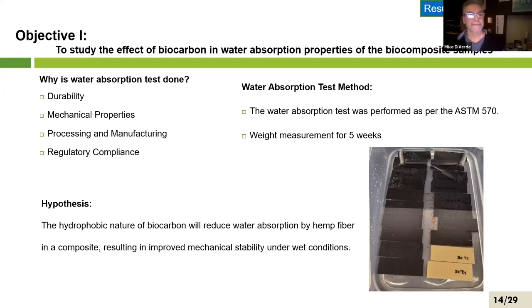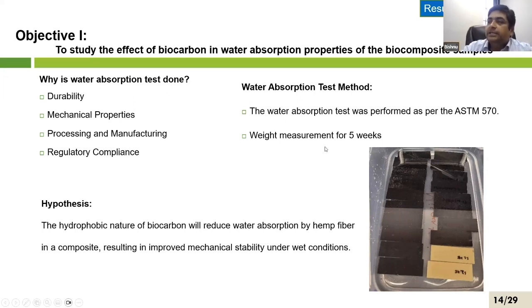No. Please continue. Yeah, so we did the water absorption test. Basically, we created this sample as per the ASTM D570. We dipped them in the water. Weight measurement was done for 5 weeks. So I think every day we collected the weight to see how much water the sample was absorbing.